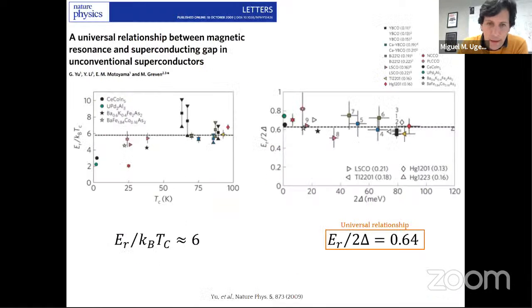Okay, and actually there's a previous paper showing a universal relationship between this magnetic resonance that should appear in the density of states and the superconducting gap. So there should be a universal relationship between these two quantities. So if you look at the ratio between the gap and the binding energy for this collective spin excitation in these many different materials. Here they collected many different spin excitations in different families of unconventional superconductors, and then you plot this ratio. Basically, all of these materials follow this universal relationship.